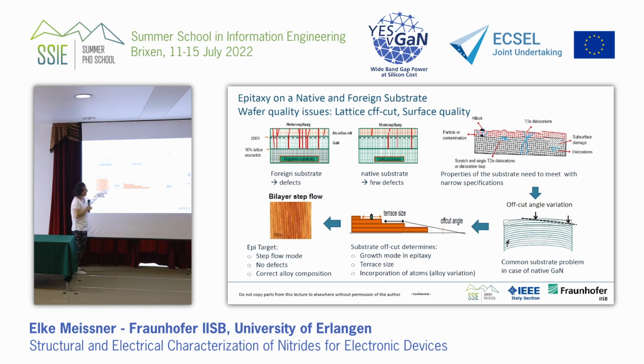And this is very delicate to the gas flow and the temperature that you're applying during the epitaxial process. What you want to have is a bilayer step flow. And if you want to create this step flow, then you have a certain window for temperature and the gas flow of your media, like the TMGa, the TMAl, so the gases that you use to deposit the gallium nitride or the aluminum gallium nitride, and this creates the length of the terrace as a response to the surface offcut.